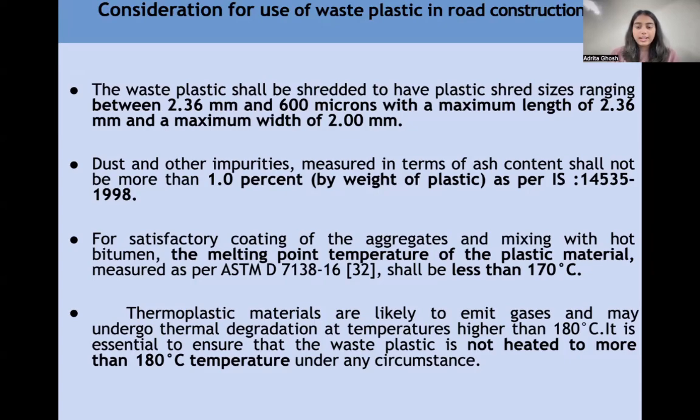Thermoplastic materials are likely to emit gases or may undergo thermal degradation at temperatures higher than 180 degrees centigrade. It's essential to ensure that the waste plastic is not heated to more than 180 degrees centigrade under any circumstance.